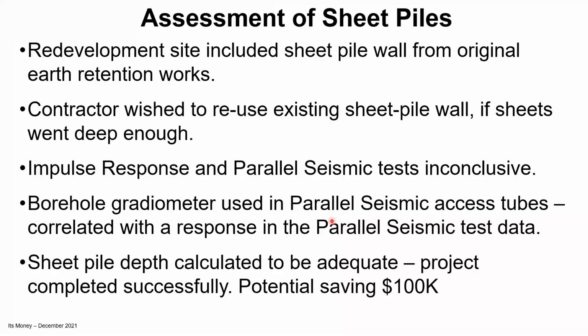So it's very likely that the practitioners using the parallel seismic test didn't take into account soil conditions, and as a result created an error that caused quite a lot of problems for the contractor until he went and physically pulled the piles out to prove them wrong. So all of these tests need to be used with a good understanding of their operating principle and of the factors which are going to affect them. And not understanding those factors is going to lead to certainly inconclusive data and quite often lead you completely in the wrong direction.